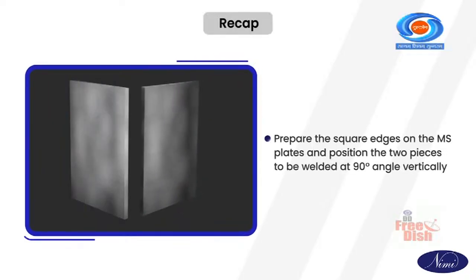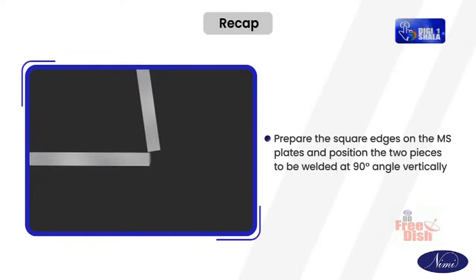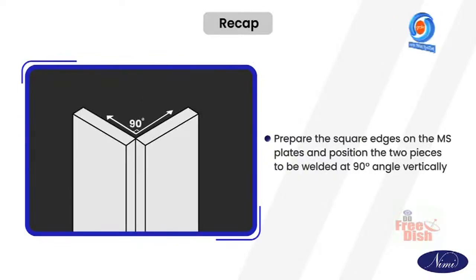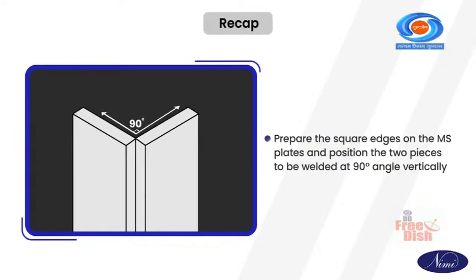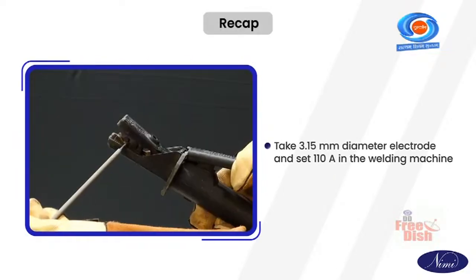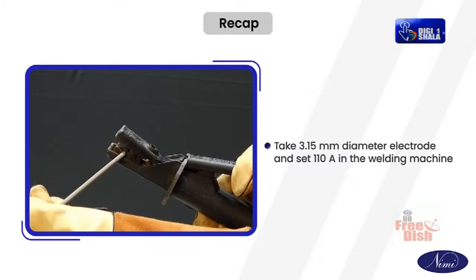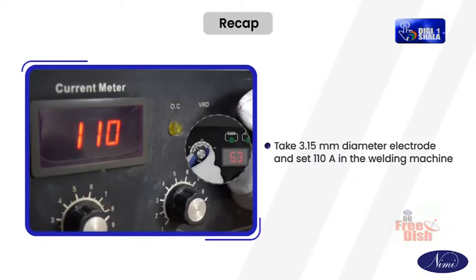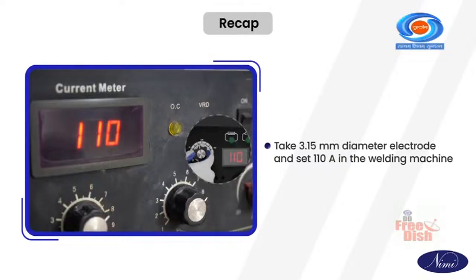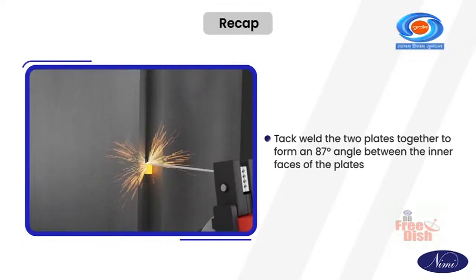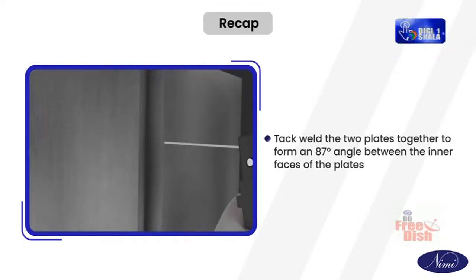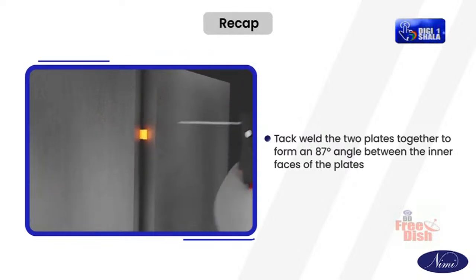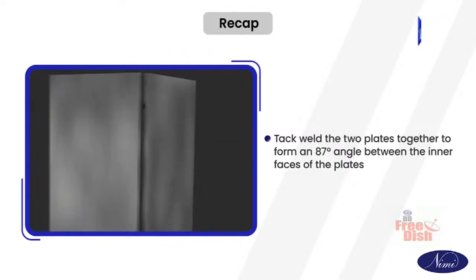Let's recap the key points discussed. Prepare the square edges on the mild steel plates and position the 2 pieces to be welded at 90-degree angle vertically. Take 3.15 mm diameter electrode and set 110 ampere in the welding machine. Tack weld the two plates together to form an 87-degree angle between the inner faces of the plates.